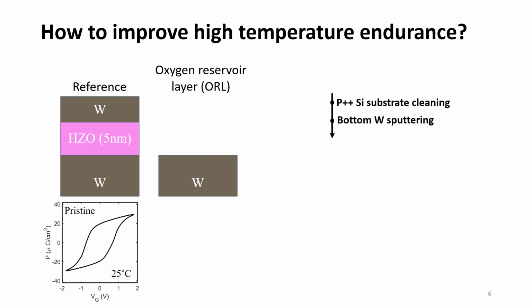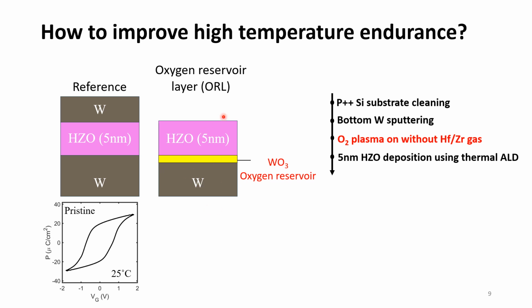So let me briefly describe how we have fabricated these devices. So the fabrication process for the reference and ORL device are pretty similar. So we first sputter 20 nanometer tungsten bottom electrode, and for the ORL device we do one extra step, which is we use oxygen plasma in the ALD chamber to oxidize some portion of this tungsten electrode to form the tungsten oxide layer, which will act as the oxygen reservoir layer here. Next, without breaking the vacuum for the ORL device, we deposit 5 nanometer HZO on top of it using thermal ALD process. And in case of reference device, we deposit this layer right after sputtering the tungsten electrode.